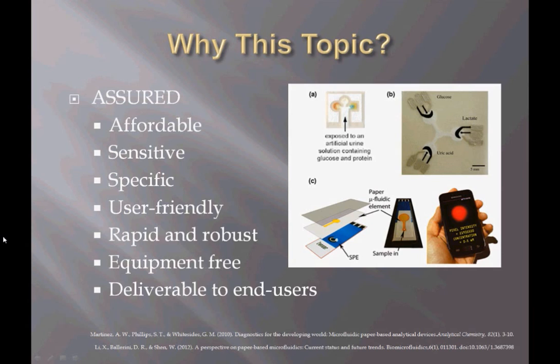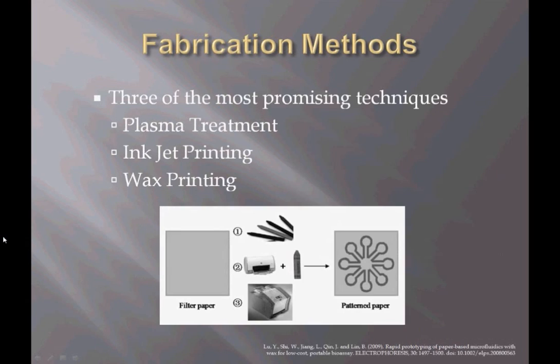The devices need to be affordable, sensitive, specific, user-friendly, rapid and robust, equipment-free, and deliverable to end-users. We'll be focusing on three fabrication methods: plasma treatment, inkjet printing, and wax printing. The fundamental principle of paper-based microfluidics is to pattern hydrophilic and hydrophobic contrast on a sheet of paper to create micron-scale capillary channels. Capillary action reduces the need for external forces in liquid transport, which is how we maintain the equipment-free requirement.